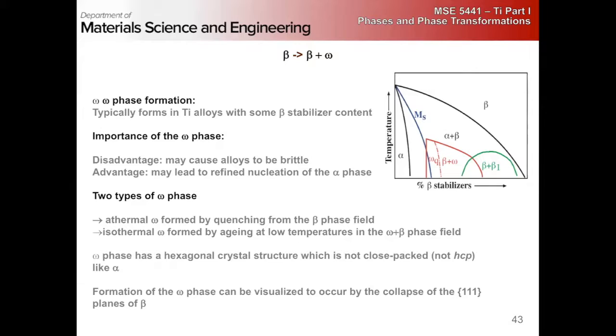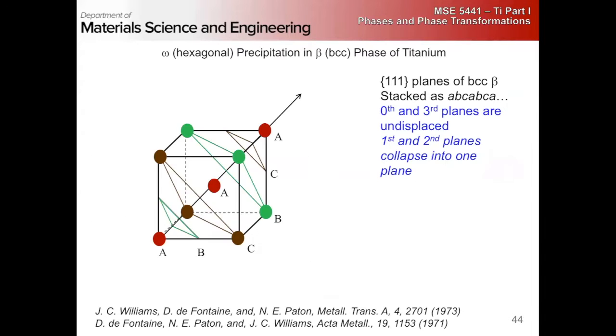So basically, these omega precipitates, all right, they act more like intermetallics or they're like purely elastic, right? You're not going to be able to cut these, right, with dislocations, just because the energy to get them to slip is going to be so high.